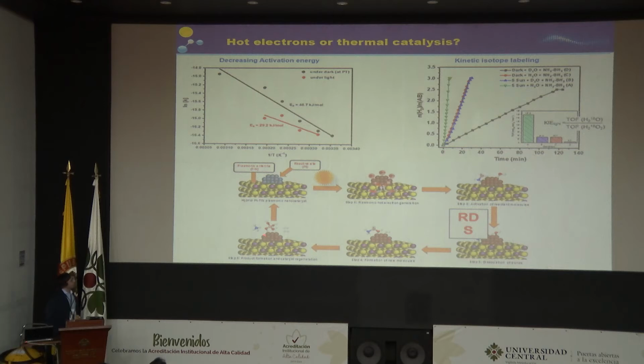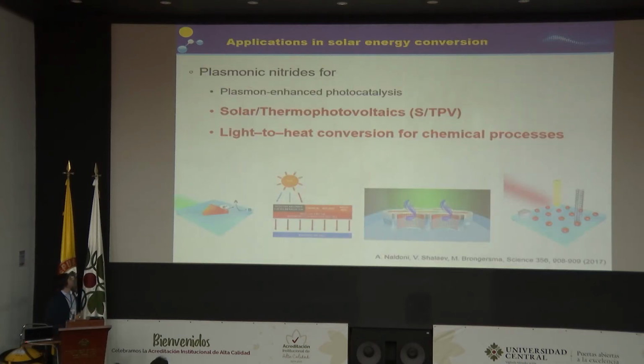And so this is just a picture of the mechanism. Basically, with the production of hot electrons, we provide much more electron density on the surface, and this accelerates the breaking of the OH bond, and so we have more hydrogen atoms that can participate in the formation of hydrogen molecules in the reactions. So now I just want to switch to the use of plasmonic nitrides in the regime of high temperatures.